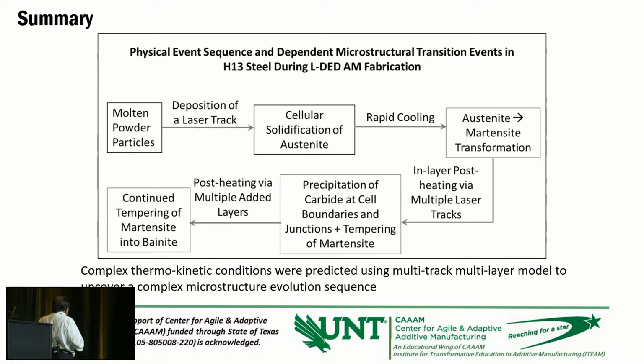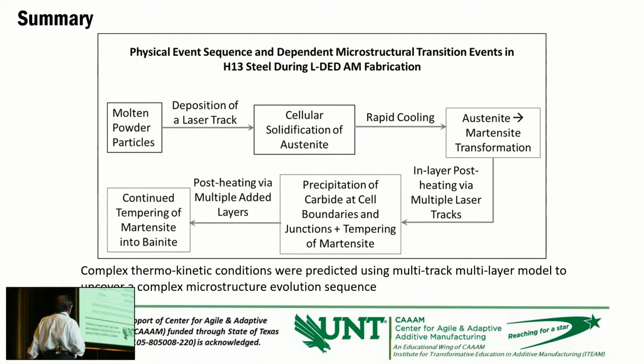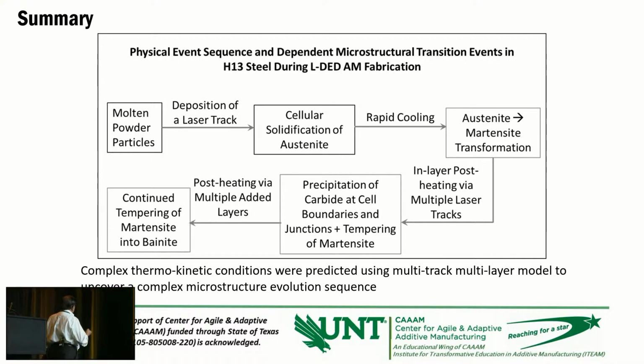such that you will be able to control the formation of these phases. Some of the phases you can avoid during the processing to get the required properties, and you can control the microstructural morphology, grain morphology, as well as the crystallographic texture. I haven't gone into detail of that side, which involves quite a bit of detail on how you control the crystallographic texture of the material by controlling the thermokinetics of the process. So all this can be predicted as well as controlled by knowing the thermokinetics of the process through computational modeling